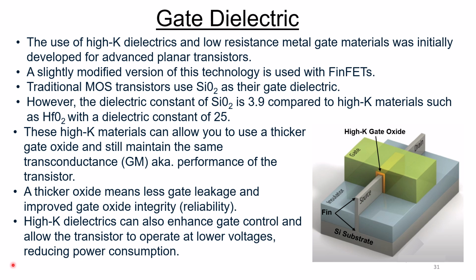These high K materials can allow you to use a thicker gate oxide and still maintain the same transconductance, aka performance, of the transistor. A thicker oxide means less gate leakage and improved gate oxide integrity, which can lead to improved reliability. High K dielectrics can also enhance gate control and allow the transistor to operate at lower voltages, reducing power consumption. And if we look at this drawing over here, the high K dielectric is drawn in yellow, and it would be surrounding the channel on all three sides.